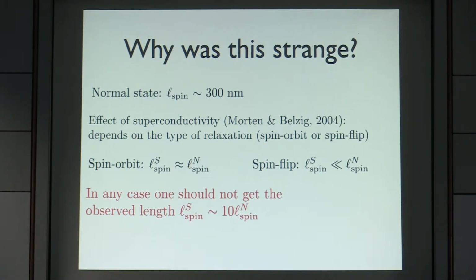Now, in normal metals, it doesn't actually matter what causes the spin relaxation. It could be spin flip scattering or spin orbit scattering. They basically work in the same way. In the superconducting case, they work slightly differently, so that the spin orbit scattering should result in roughly the same spin relaxation length in the superconducting state as in the normal state, whereas the spin flip scattering should actually result in a shorter relaxation length because of some coherence effects. So this basically meant that in any case, one should not get the observed length, which was much longer than observed.